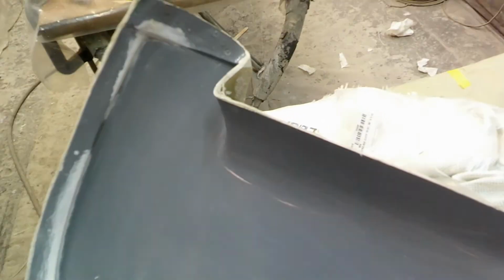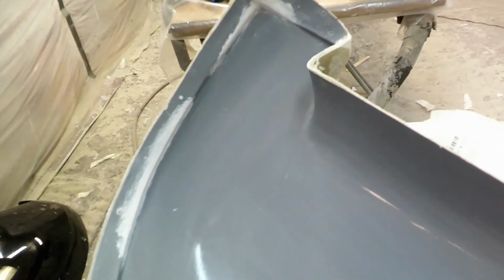Okay, so if you saw part 4 of the making of the mold for the nose bowl for Earl's Buttercup, you saw the finished result at the end of that video, where I had some small issues with the gel coat. Looking inside the mold, this is just some dirt and dust. There's a repair area that I've now repaired with some thickened gel coat. I put some adhesive filler in with the gel coat, and was able to build those small areas back up and fix them. And then last night, after I sanded that down, I had a few small imperfections, and I didn't really like the finished look, so I've put a very thin single pass of regular straight up gel coat with styrene wax in it on these 3 areas.